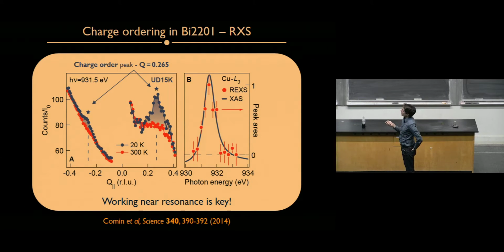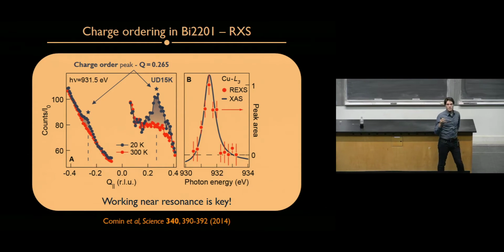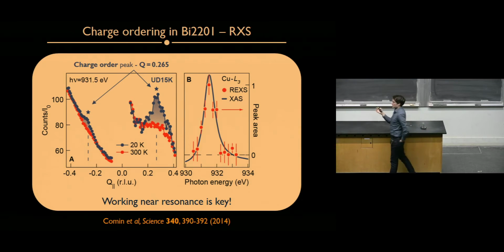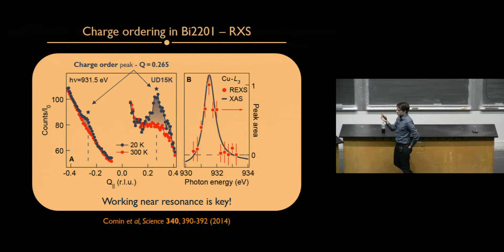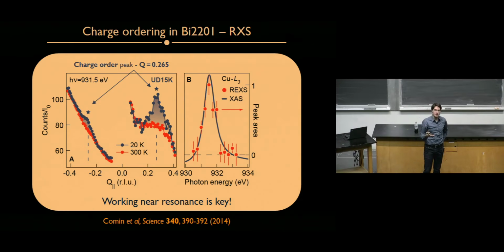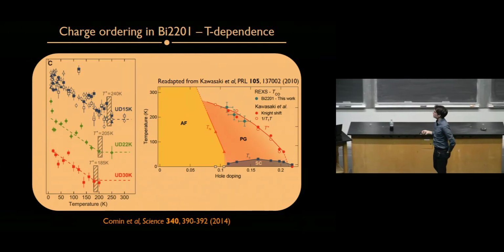If I move my photon energy away from the resonance, that is this blue curve, okay? And these are the points where I do my measurements. So this is the amplitude of this peak as a function of the photon energy, these red points. If I am right at the resonance, I see this peak has a finite intensity. But if I move away from the resonance, I become completely blind to the presence of these charge modulations. So being able to tune your photon energy increases your sensitivity to things that otherwise you cannot see, you cannot detect doing conventional crystallography.